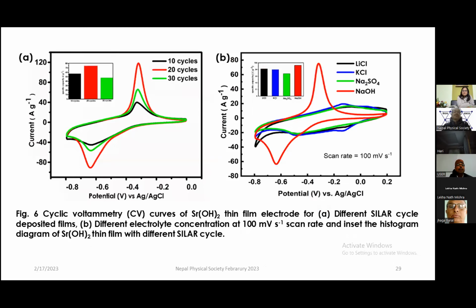Here we have the cyclic voltammetry, the CV curve of the strontium hydroxide thin film for different cycles. We have to optimize the number of cycles, that is 10, 20 and 30, and see which number of cycles of deposited strontium hydroxide gives more area. One can see that 20 cycles gives more area. This is the 10 cycle, black color, and the green one is the 30 cycle, but the 20 cycle is the best one in this case.